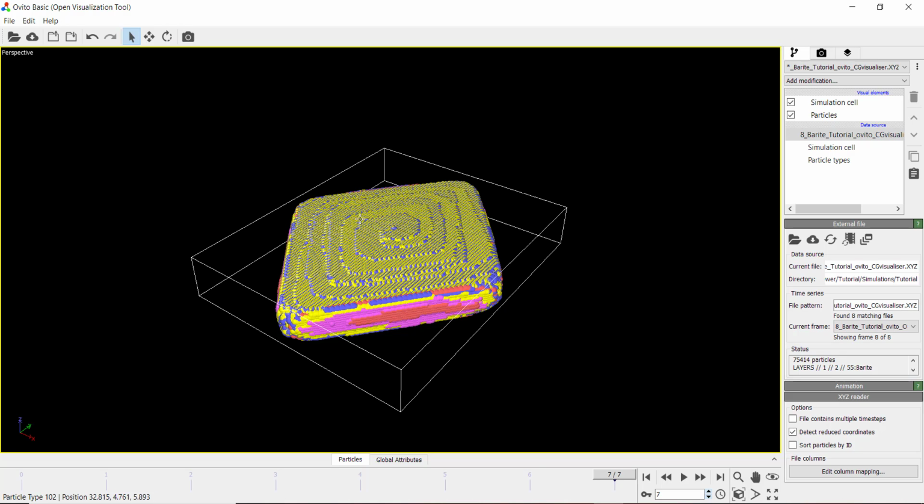So checkpointing is really useful because you can also use it to recolor your crystal. So if your layers are slightly incorrect with coloring, but you don't want to have to regrow your crystal because that can actually change the outcome due to CrystalGrower being a Monte Carlo program, you can use a checkpoint to run the simulation for just another 2 iterations, but use a different facet coloring file to define your facets.